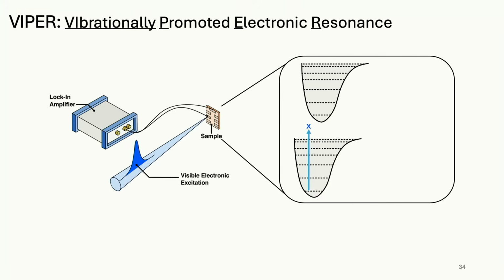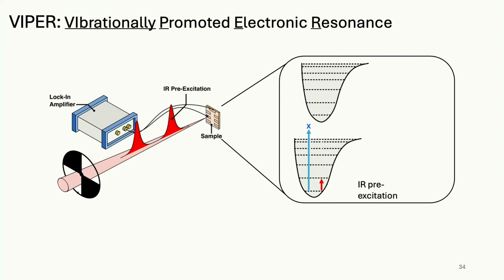So this is their experimental apparatus. They send in, here. Are you familiar with this kind of a chart? This would be like the ground state of the system, and then you could excite a vibration. That's what this red line is. This is just exciting vibration, but then you could go to excite an electron using visible light. This is infrared light and visible light. But now, if you have IR excitation first, this blue line will be enough so that you can reach the excited state. So we would say in laser language, we detune the visible excitation. So if you don't have the right vibration in the right place, you can't get any excited electrons. But if these can talk to each other, then yes, you can. So we call this vibrationally promoted electronic resonance, which is an acronym VIPER.